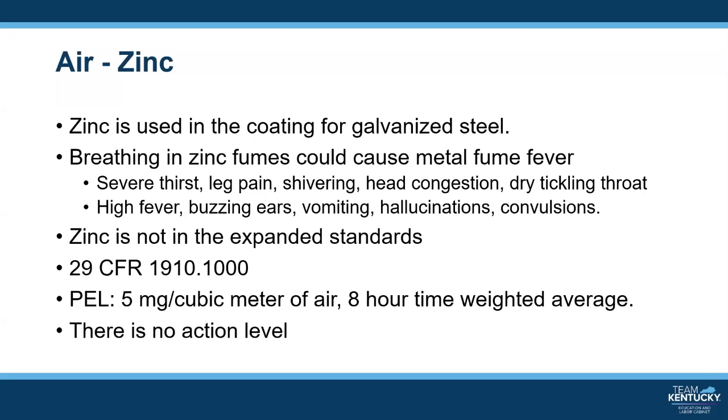The OSHA regulations for zinc are found in 29 CFR 1910.1000. The PEL for zinc is 5 milligrams per cubic meter of air over an 8-hour time-weighted average. There is no action level. This is not in the expanded standards.